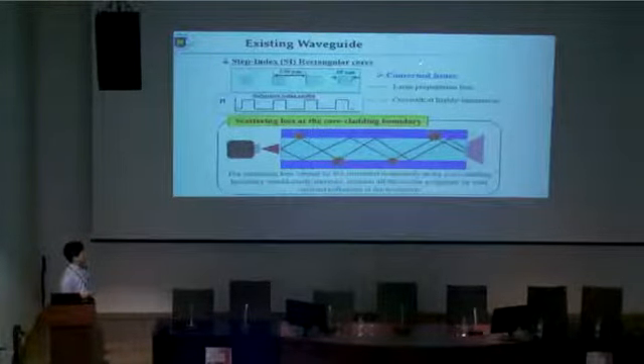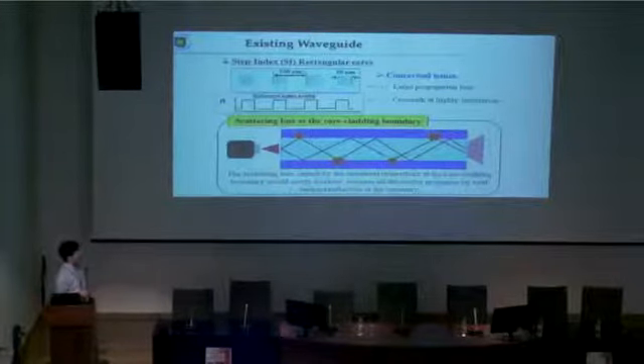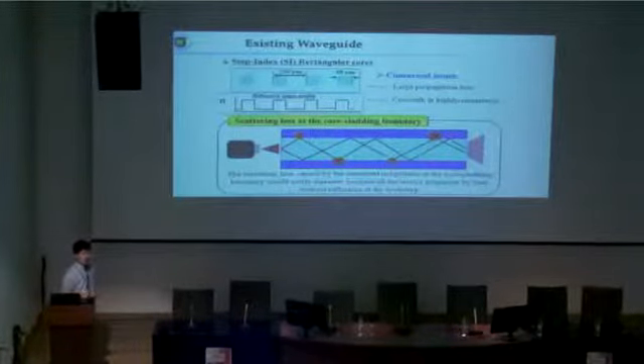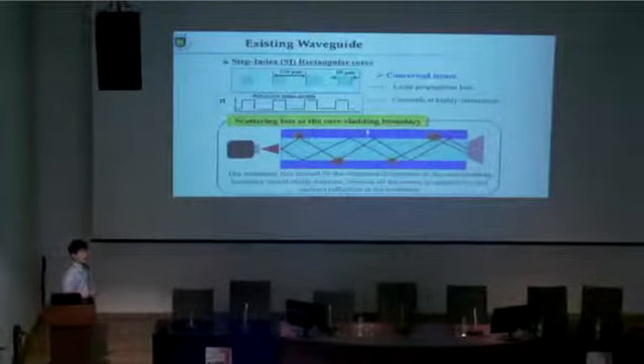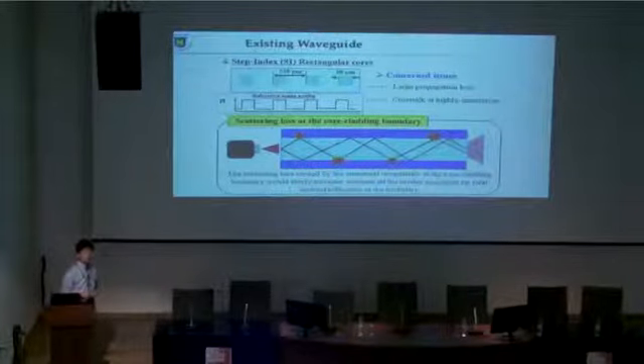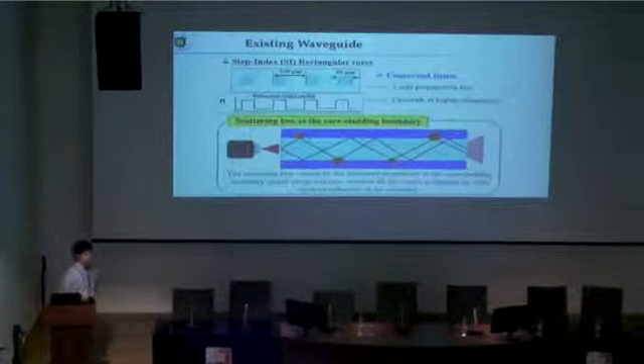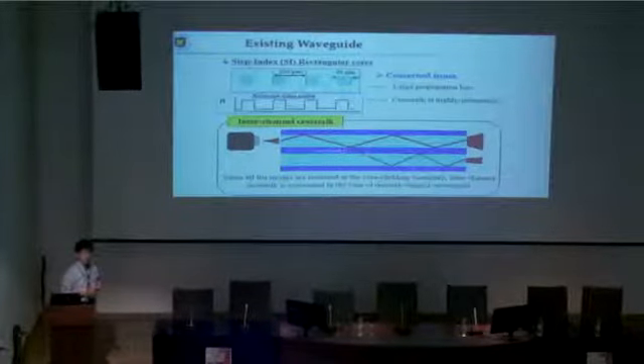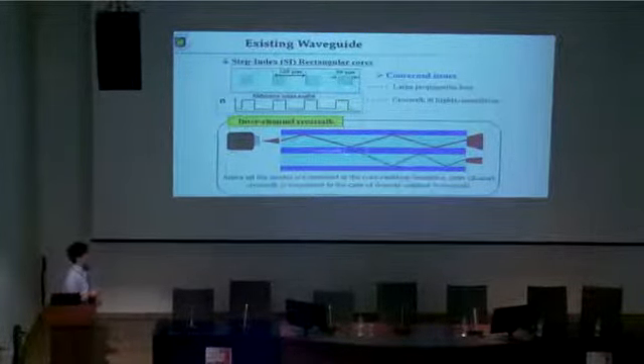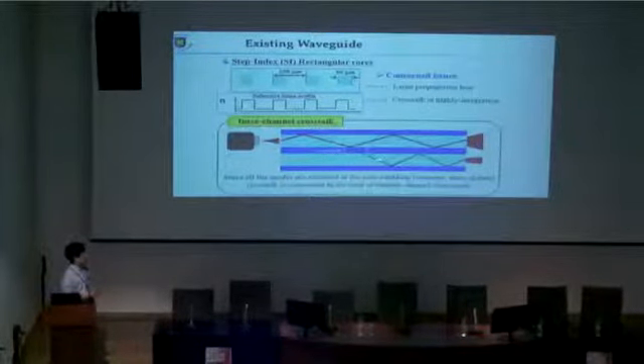However, in the case of this step index type waveguide, we are concerned about these two issues. One is the possibly large propagation loss, because if the core-cladding boundary is not smooth, the light is not completely reflected, but scattered a little bit. And then by repeating this reflection at the rough core-cladding boundary, it may cause excess scattering loss. And then for a higher density core alignment, the pitch is now 62.5 micron, as I mentioned. Then the closer cores can receive the scattered light from the main core. It may cause crosstalk.